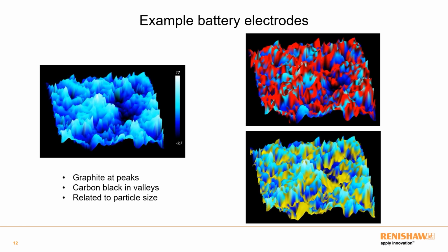Going to the next slide, we can start to combine all this information together. So the topography image is shown here, and in this case, we basically just have the change in height. On that topography image, I have shown the carbon black and the natural graphite. So in red, we have the natural graphite, and you can see that that tends to occur on the peaks of the topography, whereas the carbon black in yellow tends to occur in the valleys, and this is of course related to particle size. So the carbon black particles are much smaller than the graphites, they don't tend to stick out, and they tend to infill the areas. And obviously this is a useful piece of information which you wouldn't be able to get using Raman on its own.